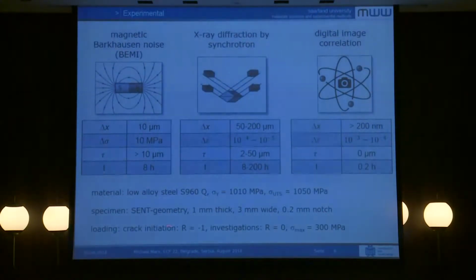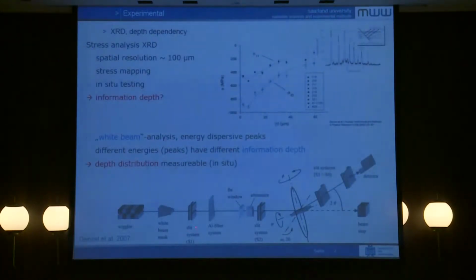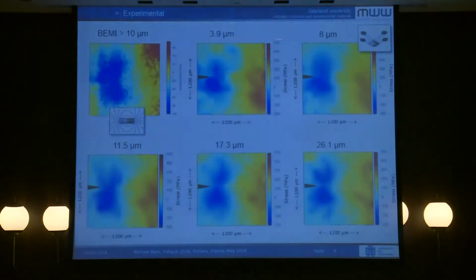And here are some details about the material we have investigated. In this case, it was low alloy steel S960 with high strength, and it was a single edge notched tension geometry. Here you see the dimensions. This is just to remember that by the synchrotron measurements we can look inside our specimen by controlling the geometry of the diffraction, and then we can have a look inside the specimen.